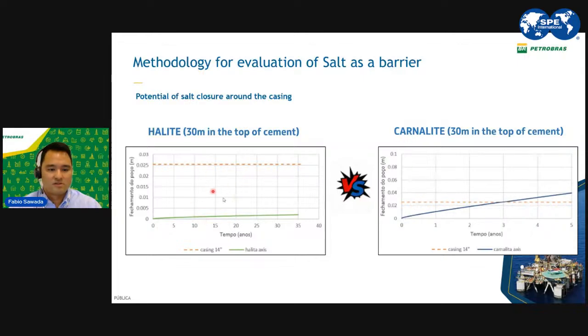In this first chart on the left-hand side, we can see the chart for halite. We can see that in 35 years, that would probably be the life cycle of a well, this halite would not reach the casing. The dashed line here shows the expected closure from the nominal diameter of the open hole to the nominal outer diameter of the casing. So in this case, this 30-meter layer of halite would not form a barrier.